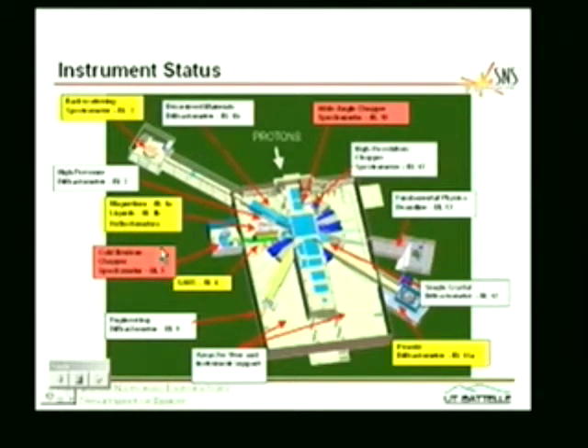2 reflectometers for studying surfaces and interfaces and multilayers. So that might be magnetic multilayers. It could be membranes. A small angle scattering instrument for studying things that are big, like proteins and polymers. And a powder diffractometer for doing structural refinement of crystal structures in polycrystalline samples.